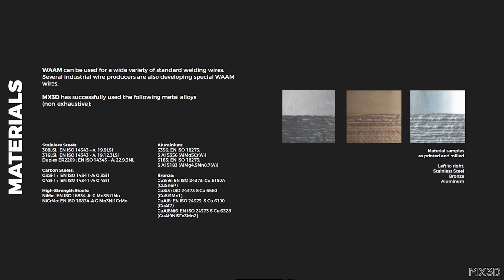On the right-hand side, I've put 3 pictures of printed stainless steel, bronze, and aluminum. And on the bottom, you can see how it has a distinct weld bead shape. And on the top, it is post-processed because wire arc additive manufactured objects can be post-processed just like any other metal object. So in this case, the wire arc is a near net shape process. And if we want to have high precision, we can post-process like on the top, and we can achieve accuracy.